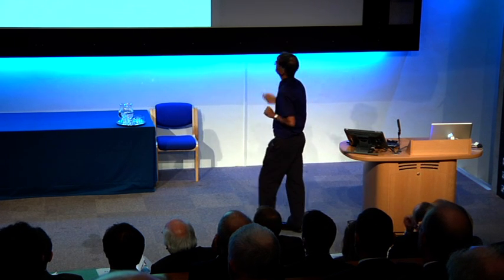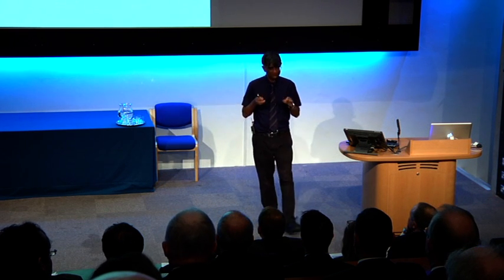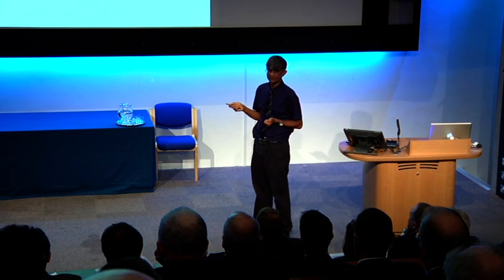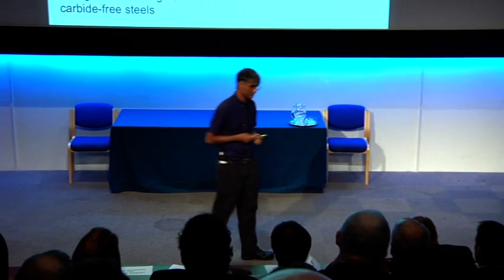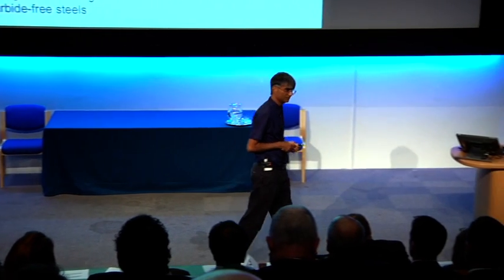The bainite transformation: about 30 years of research can be summarized in this slide. It basically forms as a plate of martensite, but it forms at a temperature where the carbon can escape from that plate into the austenite and precipitate there as cementite particles. But we can kill the reaction at this point. We can stop the precipitation of cementite by adding an element like silicon, for example, or aluminium, because cementite hates silicon or aluminium.